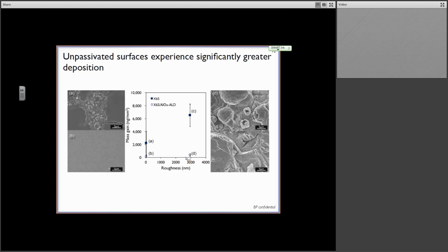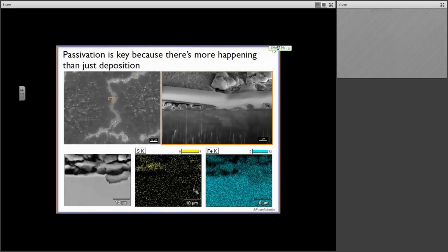Over here on D, which corresponds to this rougher data point here, again, still very low mass gain. All the contrast you're seeing here is just from the intended initial roughness that we put into these surfaces. There are examples, and I'll show you them later. We do see some areas of deposition here. Obviously, we're measuring something, but we have to look very hard for them. Okay, so in this particular case, what we can see is that roughness is important unless you change the surface chemistry. All right, and so let's dig underneath.